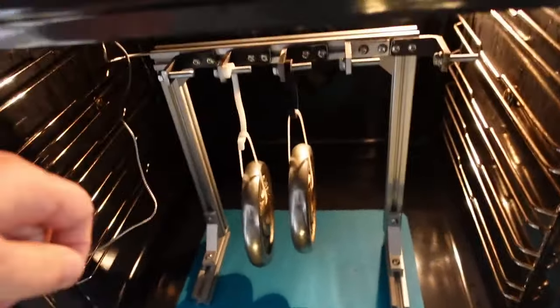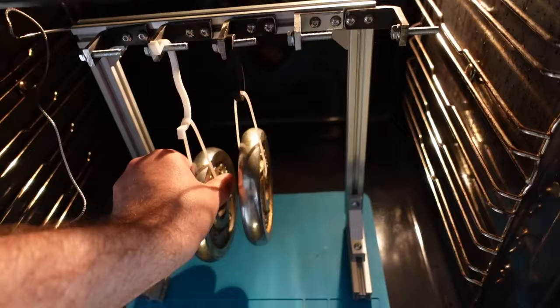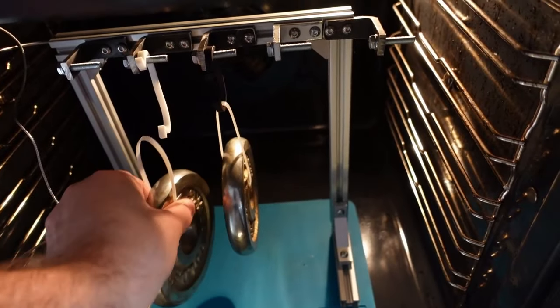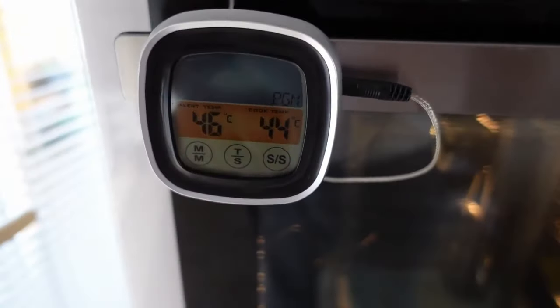Oh, the resin will fail soon. I will remove the load because it will fall down. But the temperature inside was only 44 degrees Celsius. And after 1 hour on 45 degrees Celsius, let's measure the nylon.